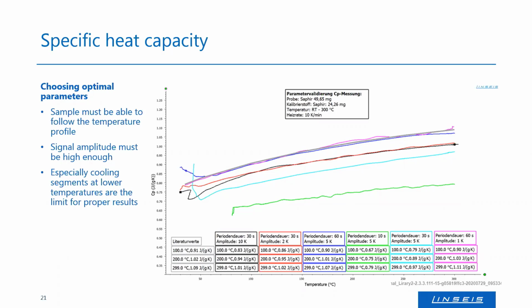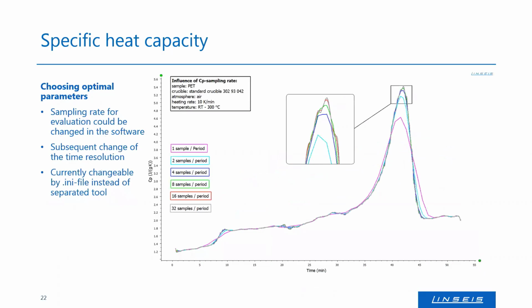Of course, it is also important to check what my heating rate is. If you, for example, heat with 5 Kelvin per minute, it would be possible to choose a lower period and maybe a higher amplitude or something like this. This depends on your needs and of course also on your sample. And that's it here. So this is normally my recommendation. In the first try, we mostly use a 60 seconds period and an amplitude of 1 Kelvin at a 10 Kelvin heating rate, and mostly also at 5. So this is a good setting.